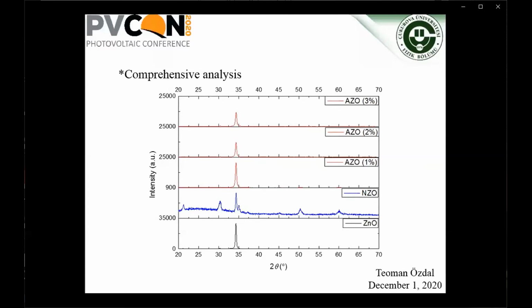As the aluminum ratio increased, the intensity of crystallinity decreased. Since the zinc ratio that participates in the crystal structure in the film is low, the crystallinity decreases as the aluminum ratio in the crystal increases.